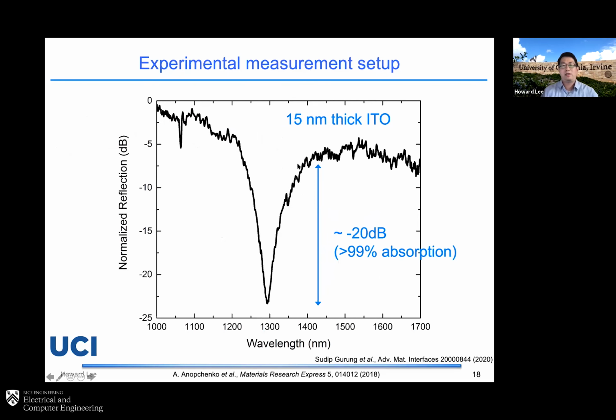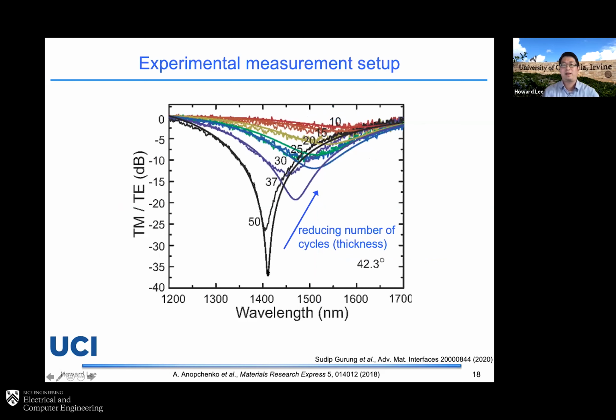And as I mentioned to you, this coupling depends quite a lot on the thickness of the material. That's why we try to use ALD to fabricate different thicknesses of the ENZ material. And you can see that the coupling actually changes quite significantly. At the same time, the amplitude of the coupling also reduces when you change the thickness here. That's why precisely controlling the thickness and ENZ wavelength is really important. And this is what ALD can do: control the thickness quite well. At the same time, the ENZ wavelength you can decide by doping the material here.